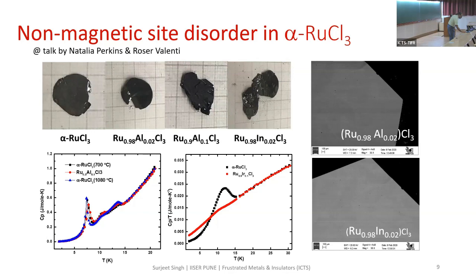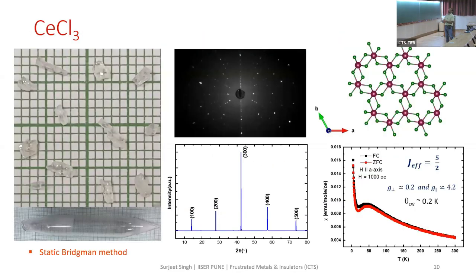So moving on, we now move to CeCl3. The structure looks deceptively similar to that of RuCl3, and this is in fact a material which has an effective spin half ground state. But the issue here is that it's not a van der Waals material. So you have the cerium connectivity which percolates also along the C direction. So it's not really something which can substitute RuCl3. The crystals are difficult to grow and also very sensitive to moisture.